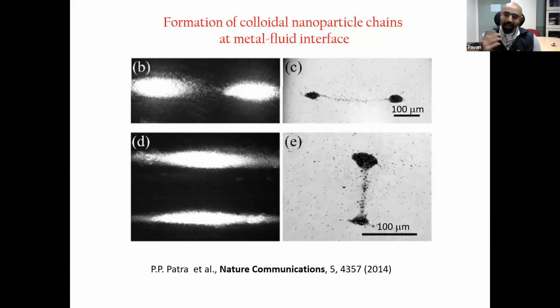Please remember, this is all happening inside a fluid, which means that when you switch off the laser, all these particles go back into your fluid. Okay, so now you can play around. You can also see that this effect is mainly driven by thermal fields, essentially an optothermal field. Because if you switch over the directionality of the excitation, the assembly always happens between the excitation fields, which means that the thermal fields are what are creating the assembly between the excitation points.